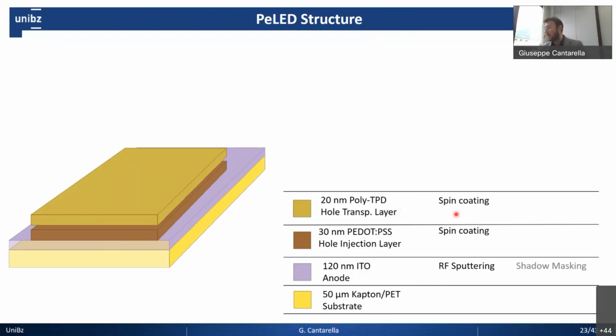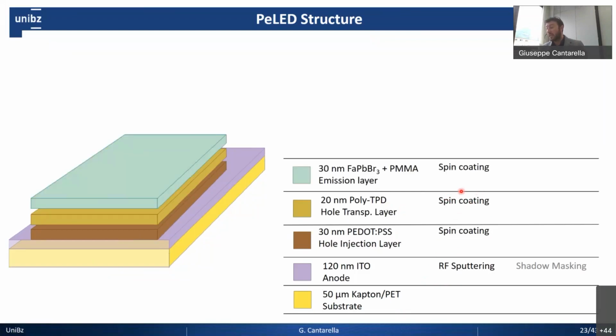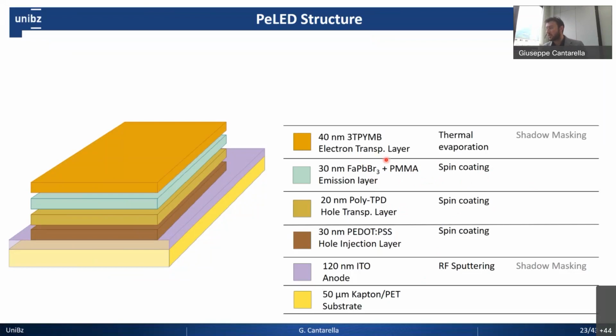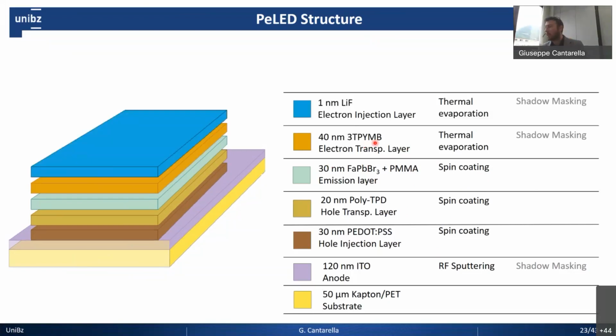So again, as you can see here, up to this point, everything could be easily spin coated. Then comes the emission layer, so the perovskite material, which is formamidinium lead bromide. As you will see in the next slide, it is a layer which allows emission in the green region, and even in this case, it's spin coated. Then as electron transport layer, we have 40 nanometer of 3TPYMB. And then to conclude the LED part, we have a very thin electron injection layer of lithium fluoride.